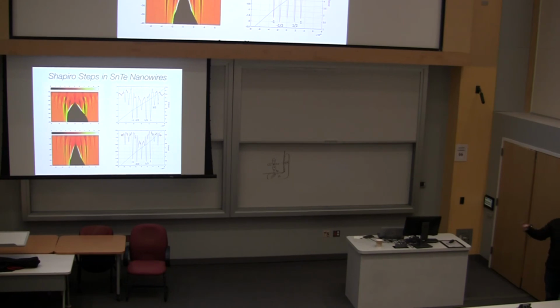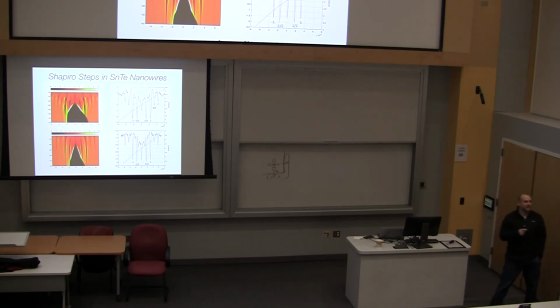You know the amplitude of each Fourier term should go down as you go to higher and higher harmonics. So you would never expect the half steps to be higher than the predominant steps. So there's some dramatic modification of the current phase relationship, which we are picking out both in our diffraction pattern measurements and in our Shapiro step measurements that we need to understand. For this particular material, we've gone through a few variations on what it could be, working with Liang Fu, with some topological phase transitions such that there's an intrinsic phase difference between the different bands of the topological superconductor and tin telluride. But the inkling I have for what's actually going on,